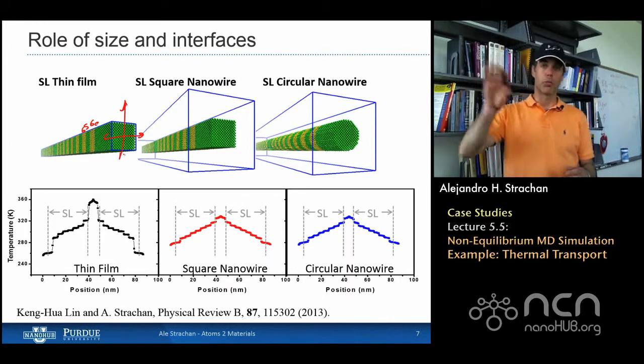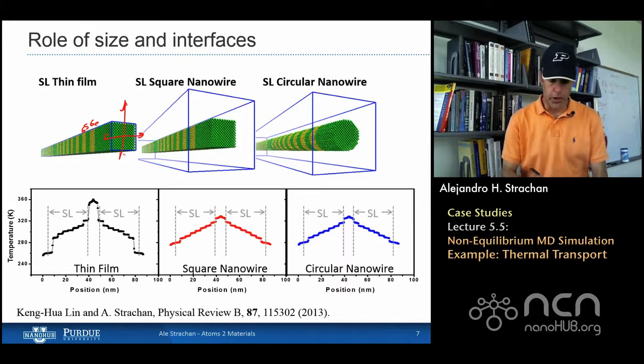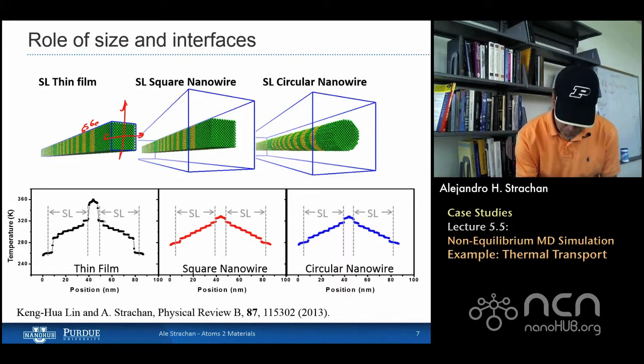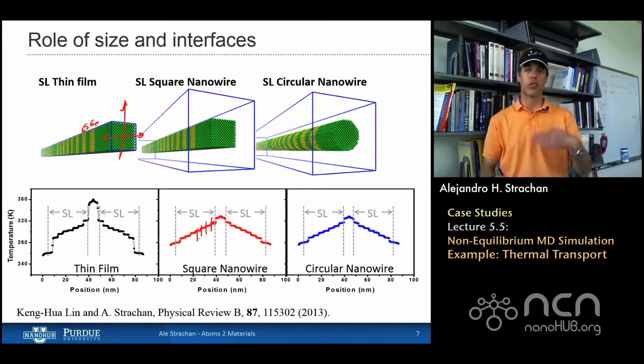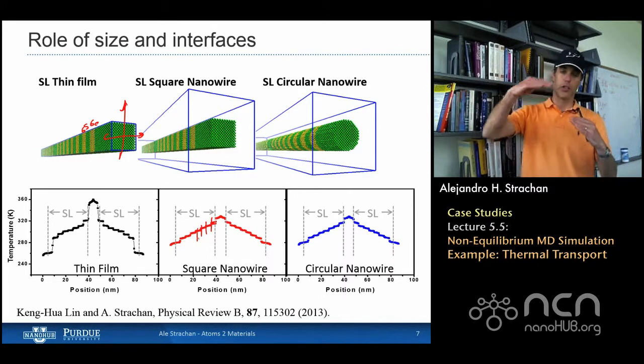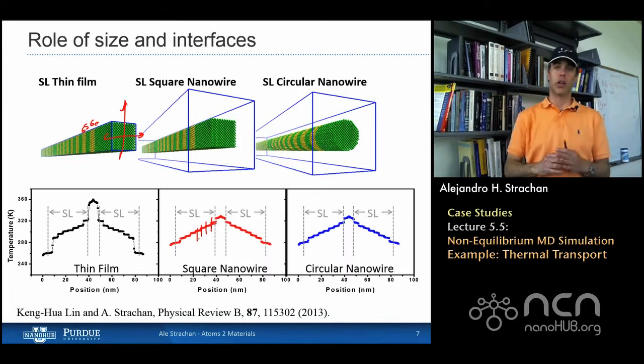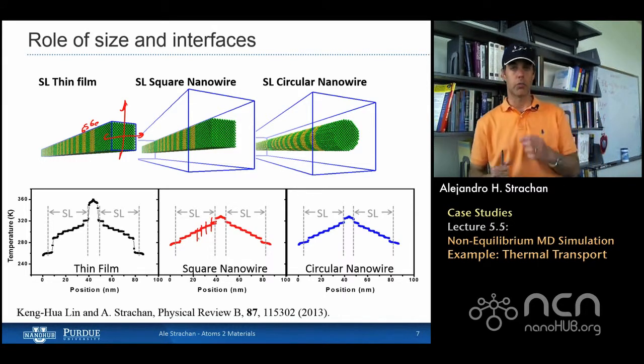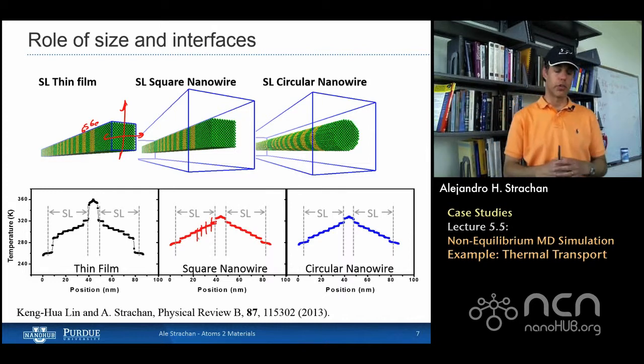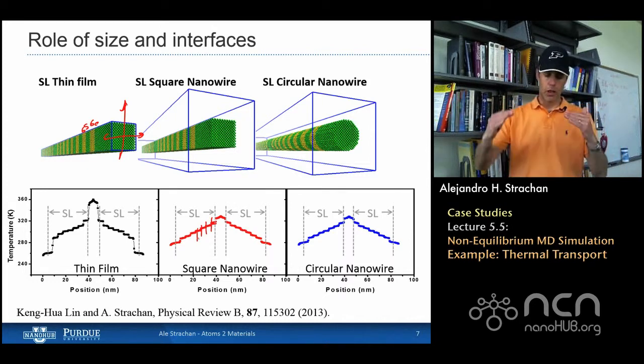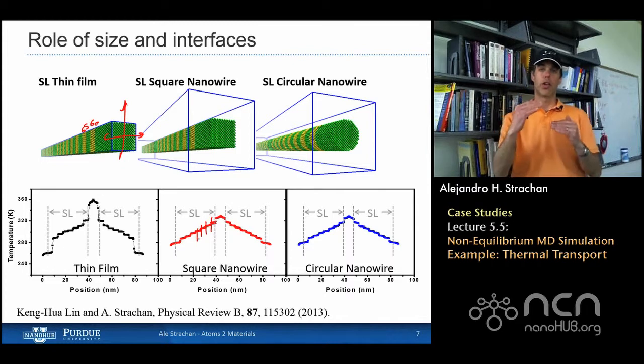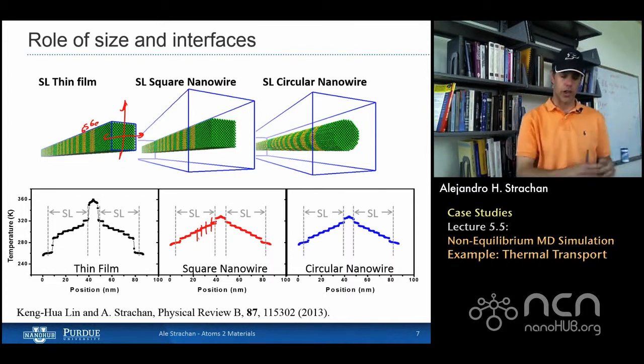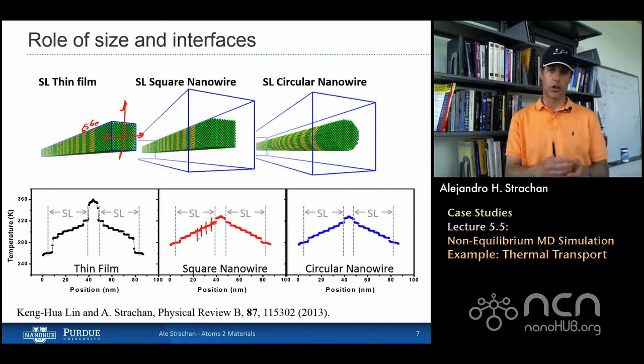So we perform this type of non-equilibrium simulation. These are the type of temperature profiles that we obtain. You can see that we can capture the interfaces, right? At each silicon-germanium interface, we have a little bit of a jump in the temperature. From that, we can measure the interfacial resistivity very accurately, and we can also compute the effective thermal conductivity of each section of the material. So a lot of detail that you get out of this simulation.